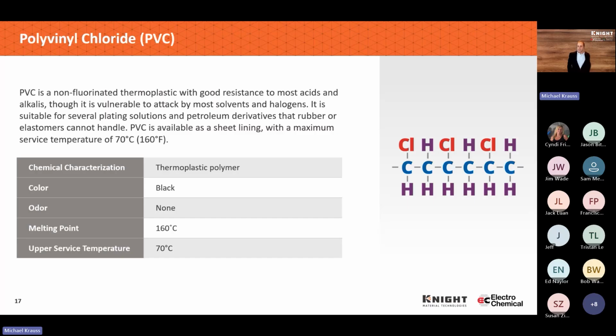So when you start looking at materials like this that are modified, a general spec like PVC can be misleading, and you need to be careful both in terms of the corrosion data that's out there, but also in terms of the lining materials, because there could be a difference between one flexible PVC grade and another. From a chemical composition, as you see here, we're starting to replace some of these hydrogens, and in this case with PVC, you can see 1 of every 4 hydrogens is replaced with a chlorine molecule.